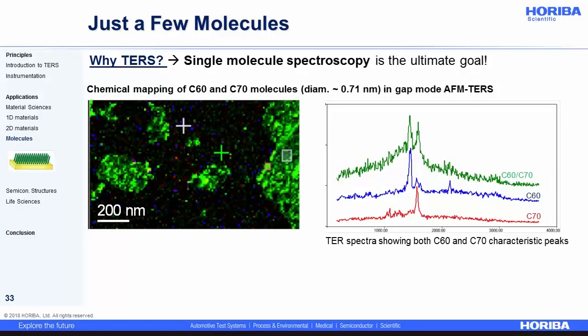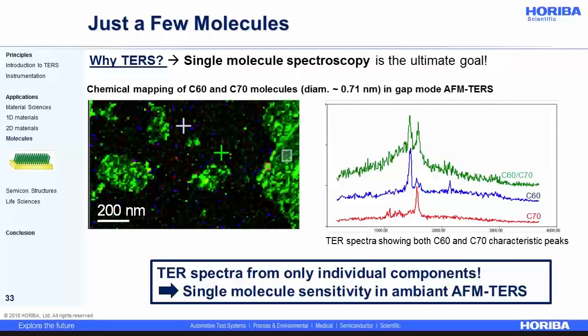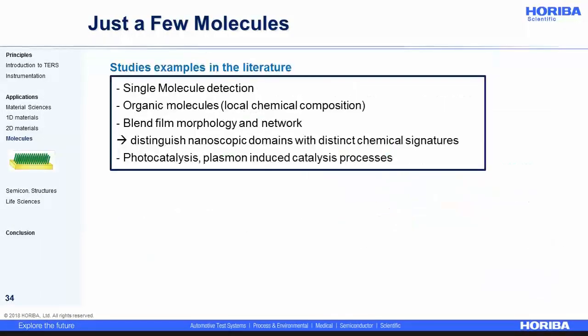So we can see on this TERS map that on a single pixel, either blue or green, we were able to obtain the unique spectral signature of either the C60 or the C70, not both of them at the same time. And having, through the TERS spectra, those individual components is a clear signature of this single molecule sensitivity that has been achieved here in ambient TERS measurement.